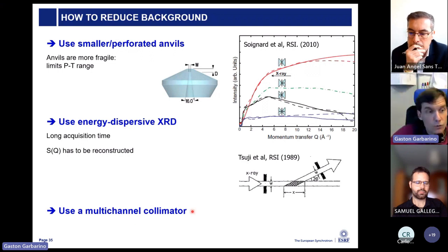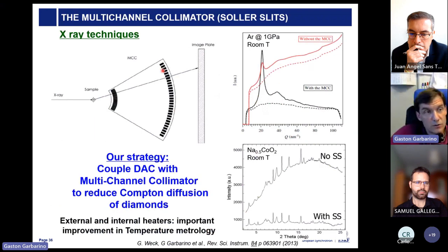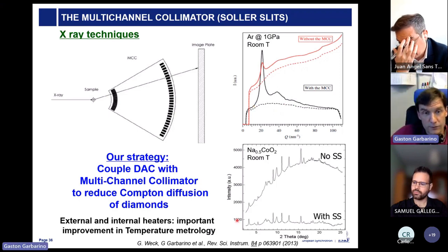So for this, there were many ways to try to reduce the signal coming from the surroundings, as you can see here. And one was to try to use a multi-channel collimator. Multi-channel collimator is only a series of slits that allows you to reduce the signal coming from the surroundings, because it's blocked by the slits. Okay, so at the end, what you see when you rotate this apparatus is to clean the background around the sample, and you can pass from something like you can see here. This is argon at 1 GPa. This is the signal of the background, and this is the signal of the sample plus the background, to the black lines in which you can really see the reduction of the background and the improvement of the signal over background of your sample. And this is not only valid for liquids, but also for solid materials, as you can see here in this particular example.